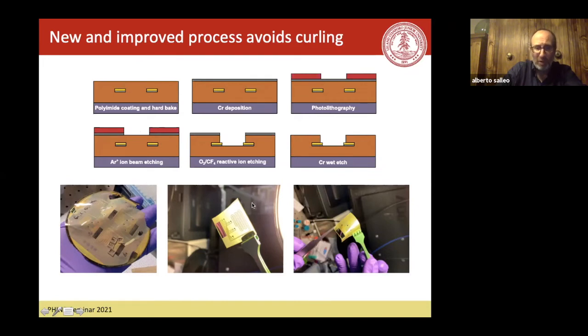this works beautifully. As you can see, we can make these coupons that are sort of chips, but they're not now on a rigid substrate. They're all on polyimide, so they're flexible and they can adhere to the skin, and we can make entire wafers of it. Right? So people can do this by printing, but we can actually make it on wafers using all equipment in the SNF that's completely compatible with standard silicon processes. So this is in principle scalable, just the same way you can scale the fabrication of computer chips.